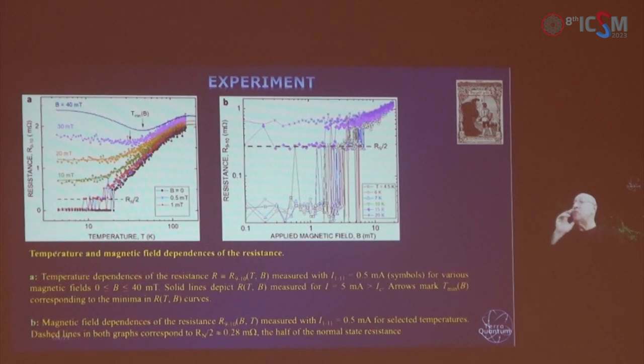And now the remarkable thing we see is that at this metastable state, the resistance is exactly half of the normal resistance, which appears as soon as our superconducting behavior disappears. This is a very interesting observation, which we explain a little bit later. So this is the demonstration of this metastable state, half of the normal resistance, which appears in both the temperature dependence and the magnetic field dependence of the resistance.